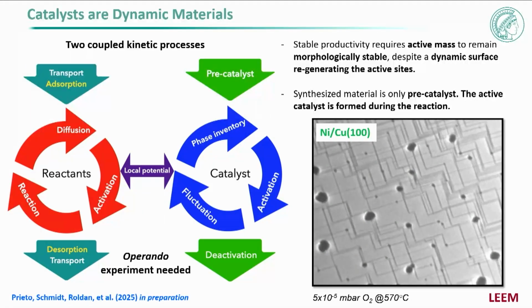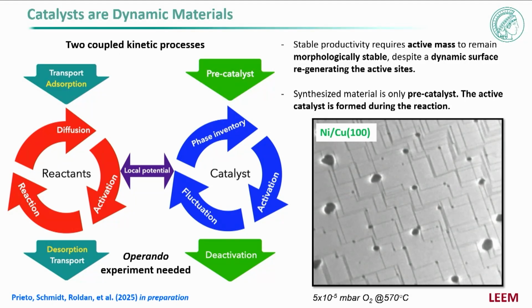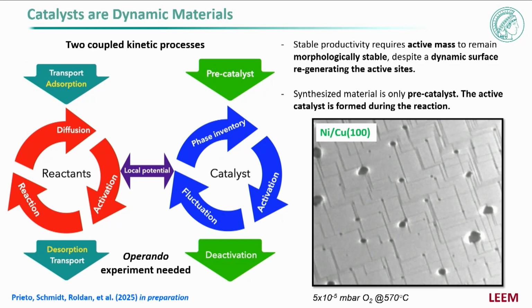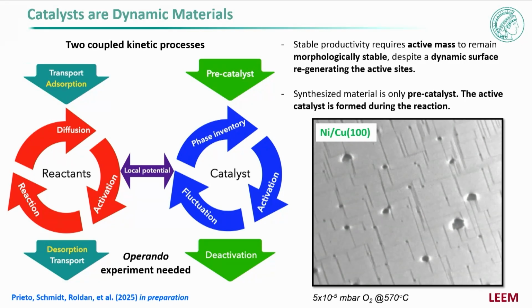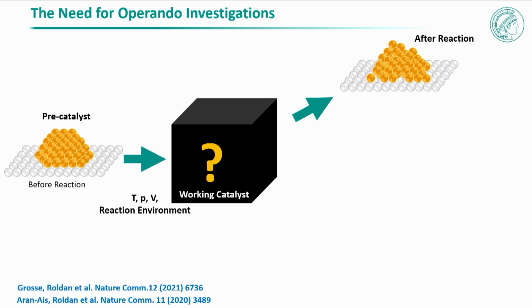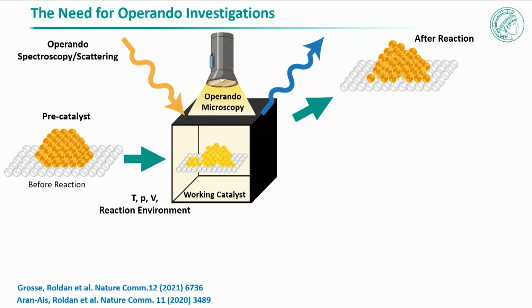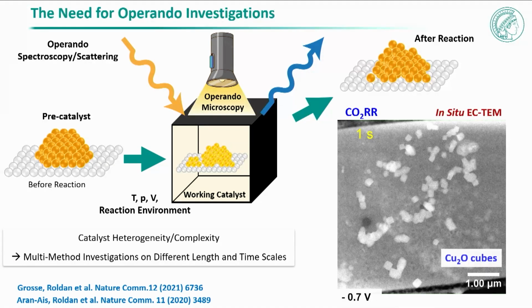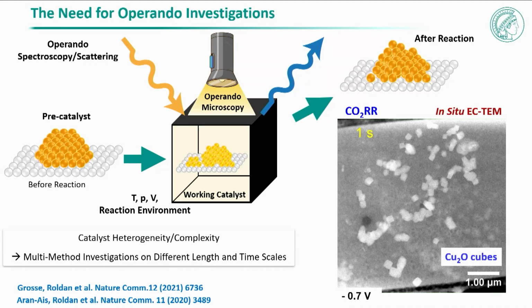So for many years, people in catalysis have been trying to explain that catalysts are stable materials, that catalysts don't change under the reaction, and certainly they are not dynamic, and you can see from these pictures that this is not true. So there is still a lot of work to do. If we are thinking about how we do this, we spend a lot of time as organic chemists preparing a pre-catalyst. Then you go under reaction conditions. We don't know what is happening here. And then you get maybe a lot of details about the catalyst after the reaction. But if you want understanding, and the understanding will allow you to tune the characteristics of the pre-catalyst so that you get the ideal working catalyst, then you need to combine microscopy and spectroscopy under realistic conditions, and this means under operando conditions. So you are going to see in my talk how we do this and why this is relevant for green hydrogen production.